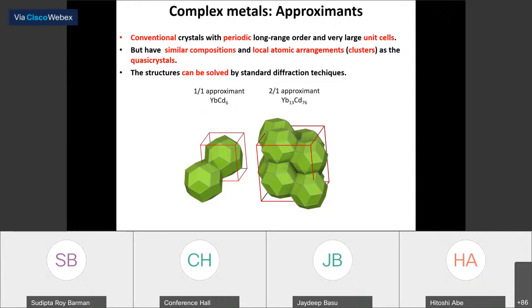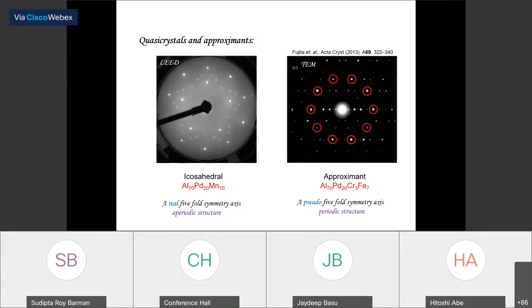So if you compare, for example, the surface reciprocal lattice as we find by LEED or by ETEM, if you look at the reciprocal lattice points, in the quasicrystals, you can see the beautiful five-fold order, whereas in case of the approximants, you do not see five-fold order. And so that is the major difference between the approximants and the quasicrystals.